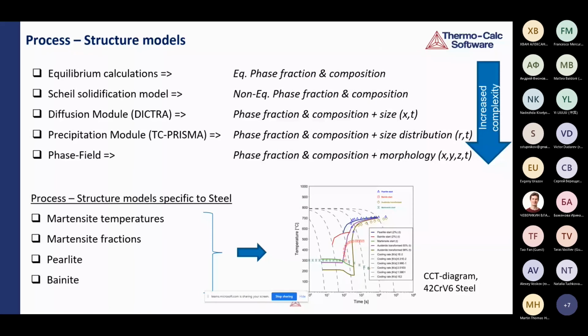So these process structure models, as we call them, as you can see to the right, the blue arrow, increase in complexity. If you're going down, you can start with equilibrium calculations, for example, to predict phase fractions and compositions. Then you can use a Scheil solidification model, and then you will have non-equilibrium phase fractions and compositions. With the diffusion module, you will add the size into it as well. With the precipitation module, you will be able to add size distribution as well, and then you finally have a phase-field approach where you can also do the morphology, and then it starts to be more and more complex.